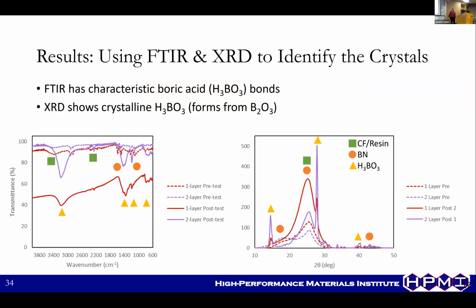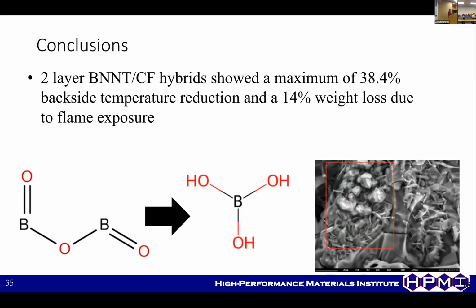And then further, we want to find out more about what those crystals are. FTIR has revealed that they have characteristic boric acid bonds, and then the XRD shows the crystalline H3BO3, which forms from that B2O3. So we've discovered what these crystalline surface structures are from FTIR and XRD. So exciting that we have a potential not only manufacturing method, but potential material that can protect from these harsh, extreme environments and still maintain their structural stability.